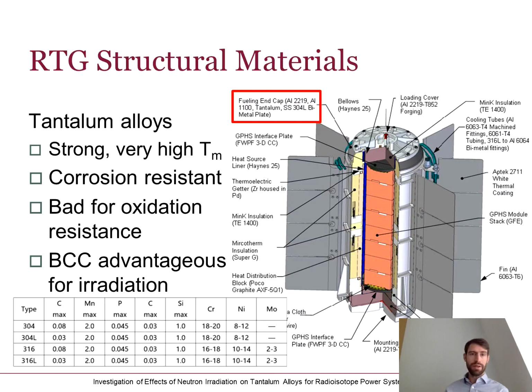Tantalum has a very, very high melting point, close to 3,000 degrees. It's quite corrosion resistant, but potentially bad for oxidation resistance. So one of the projects we have going on at the moment is oxidation resistant refractory metal alloys, trying to find this balance of properties and see if we get a better overall performance. In this case we use compositions quite close to tantalum, with minor alloying additions, and we're looking at whether we can develop new alloys in that regard.